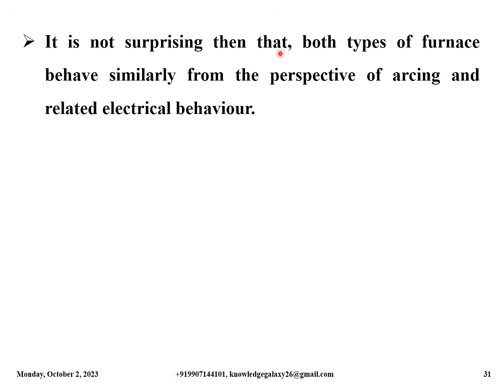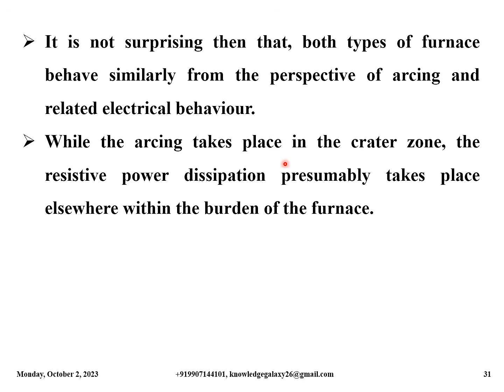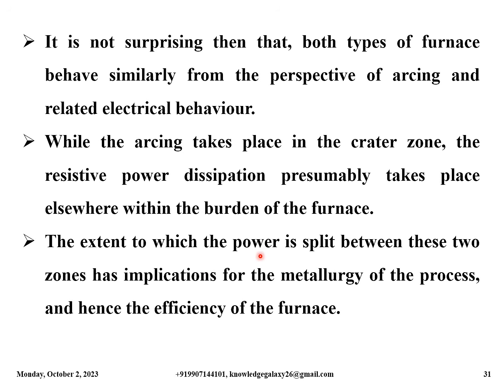It is not surprising then that both types of furnace behave similarly from the perspective of arcing and related electrical behavior. While the arcing takes place in the crater zone, the resistive power dissipation presumably takes place elsewhere within the burden of the furnace. The extent to which the power is split between these two zones has implications for the metallurgy of the process and hence the efficiency of the furnace.